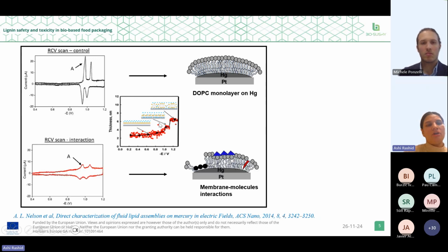In the presence of membrane active materials, different changes occur in the RCV plot and are interpreted in terms of their interactions with the membrane. For example, an increase in the constant current region indicates the penetration of the membrane active materials into the hydrophobic part of the membrane due to changes in dielectric. Any peak suppression or shift in peak along the potential axis may be associated with either the adsorption of molecules at the surface or replacing the lipid molecules.